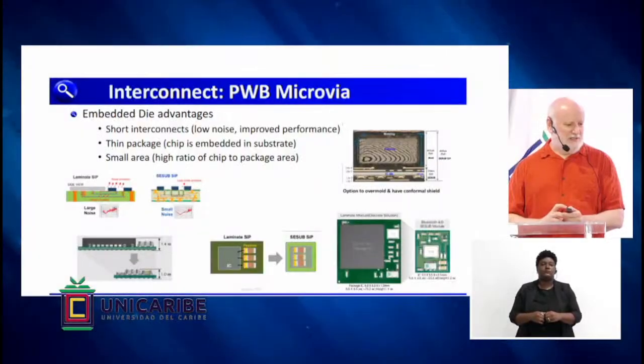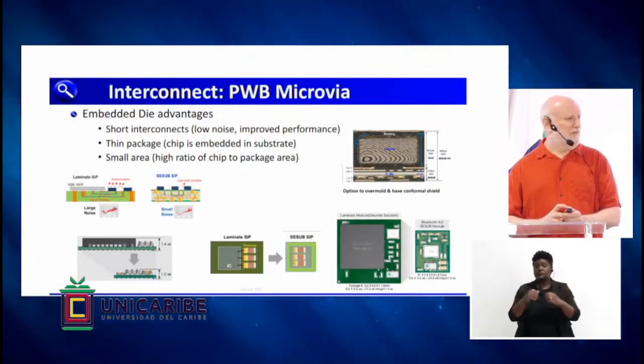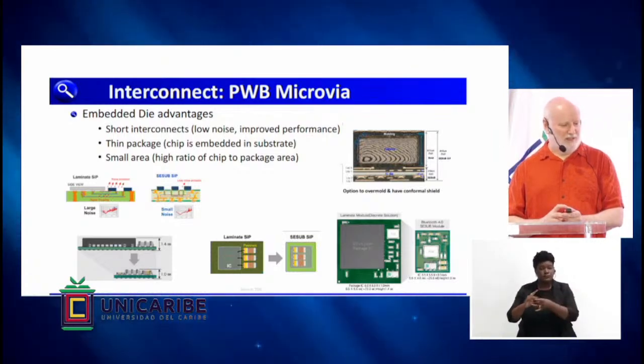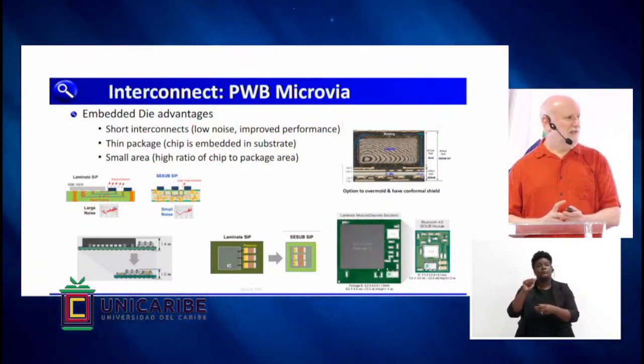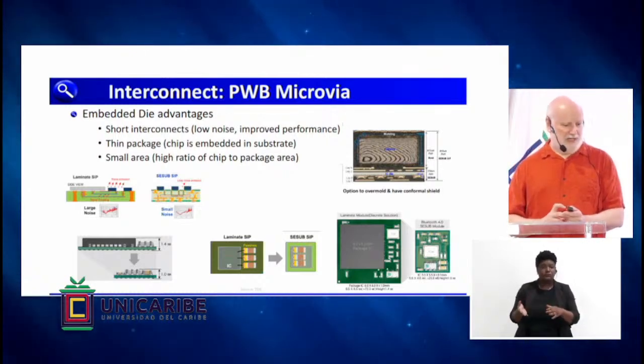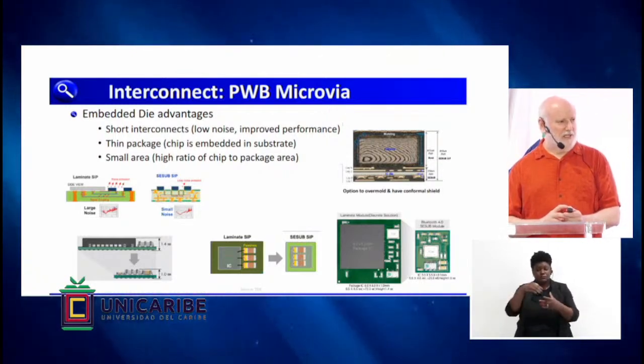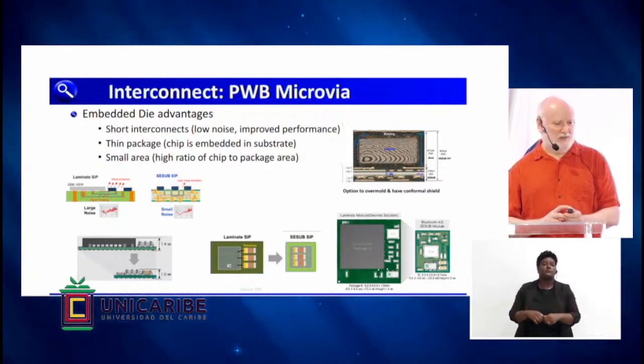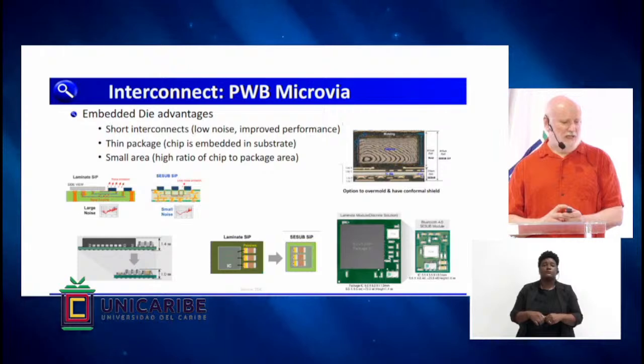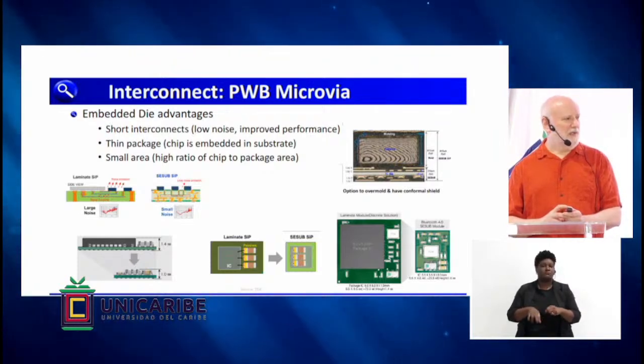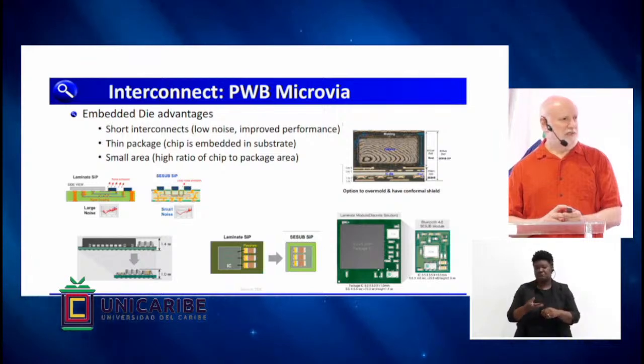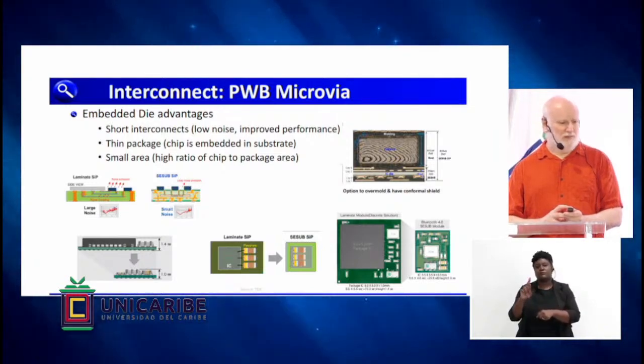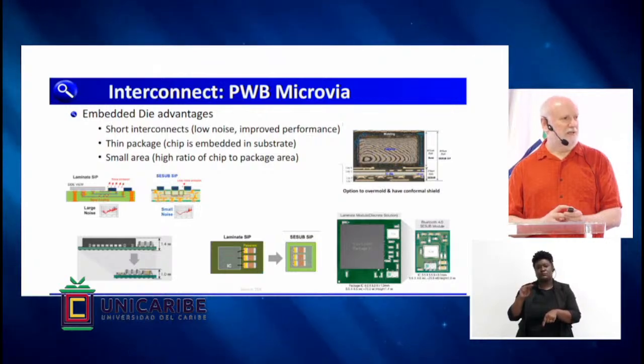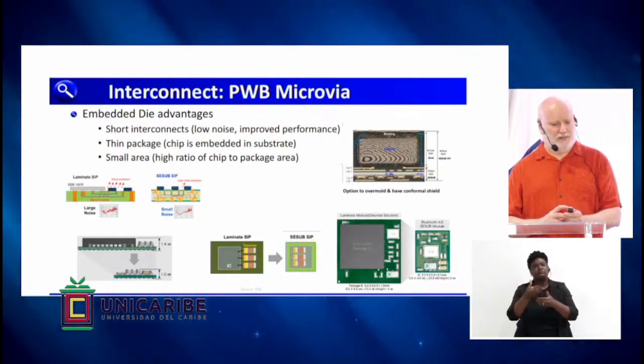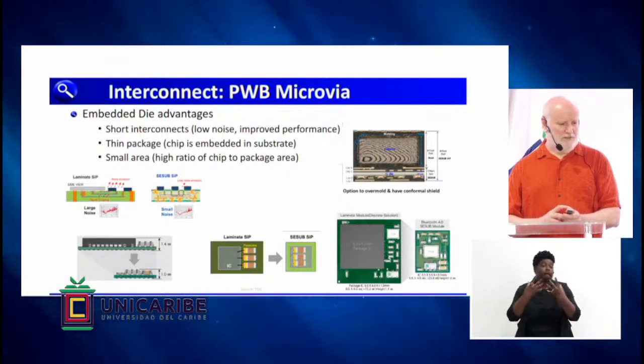So you can imagine there's certain advantage to this. You can have short interconnects and thin packages because your chip is inside the substrate itself. Small area, and it opens up the package, as the last slide showed, for other devices to be mounted. But it hasn't really taken off in the packaging world. It's not widely used, and I think part of the reason is that typically you would have to go to your laminate substrate supplier to initiate this process, and most laminate substrate suppliers really don't understand packaging technology or dealing with wafers and chips, so not widely used.